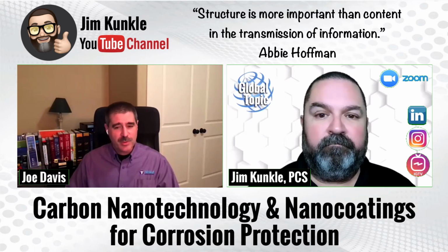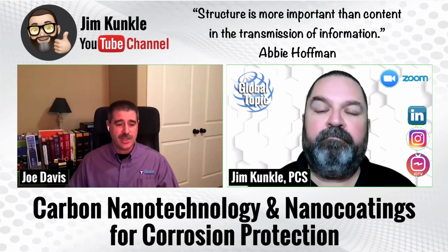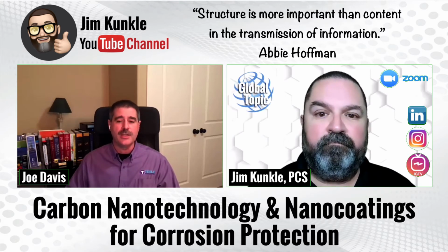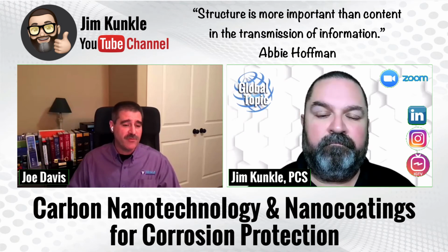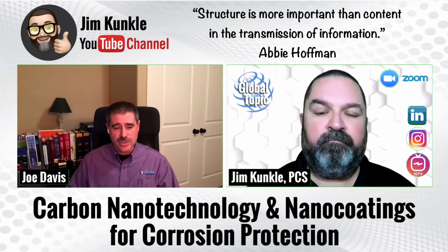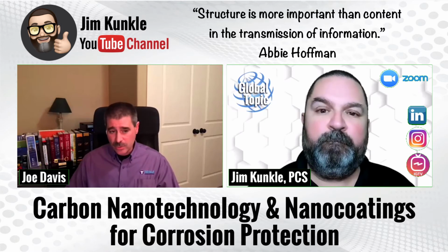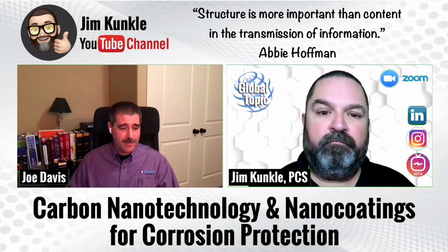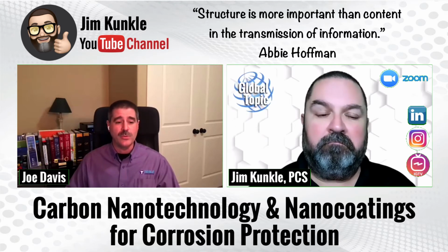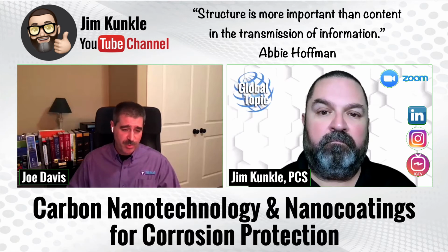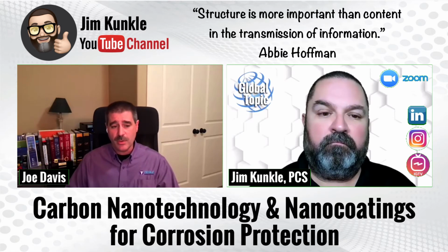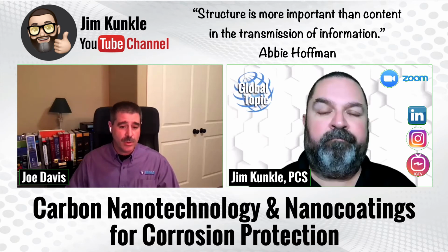The other benefit would be edge retention. And so that's big in the industry right now. Traditional coatings try to address it with a stripe coat. What we're finding, a relatively new finding for us, is that the edge retention ratio of our carbon nano zinc primer exceeds 100% in many cases. And so you don't have to have secondary surface preparation, and you don't have to have a stripe coat anymore, which is a huge time saving and benefit to asset owners.